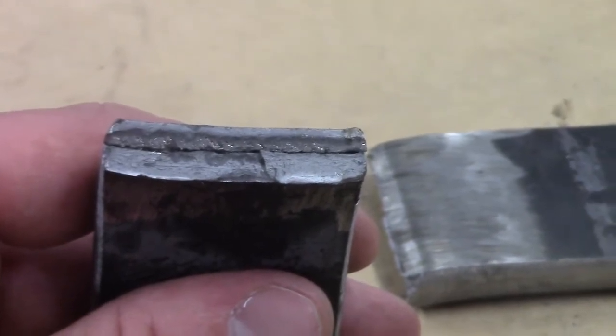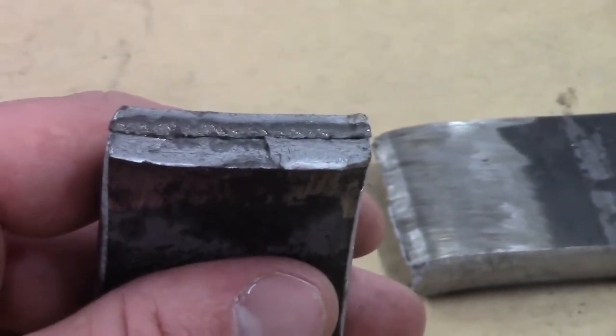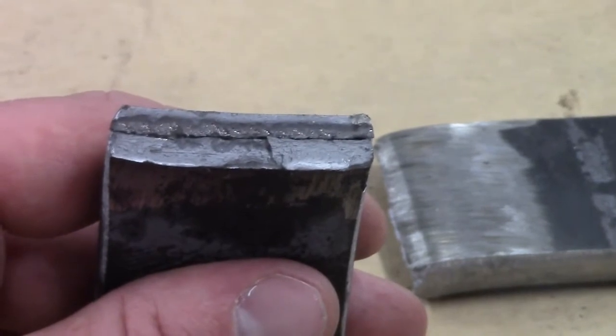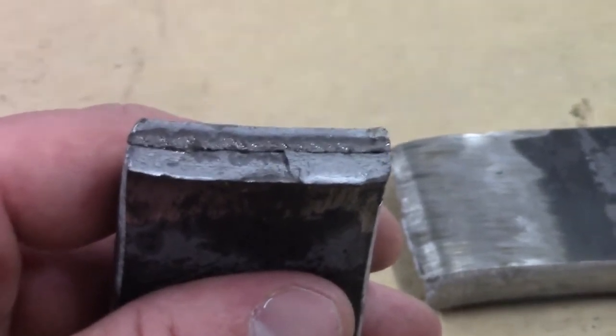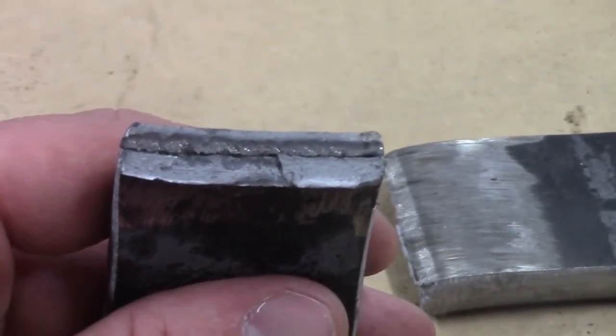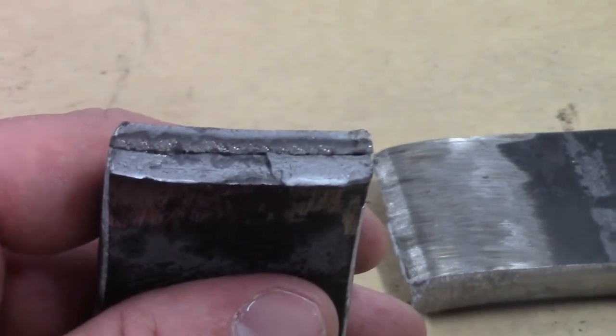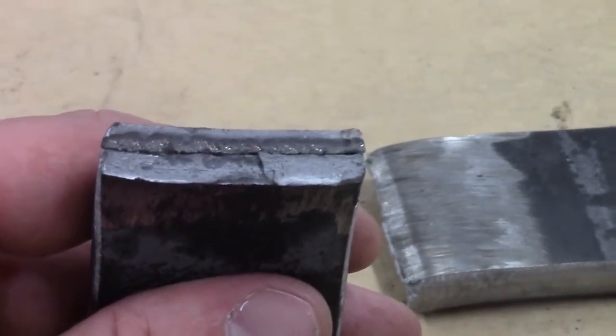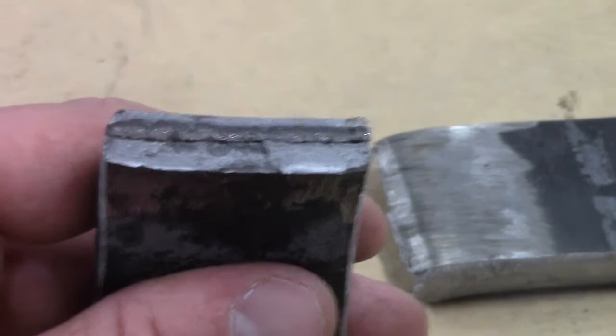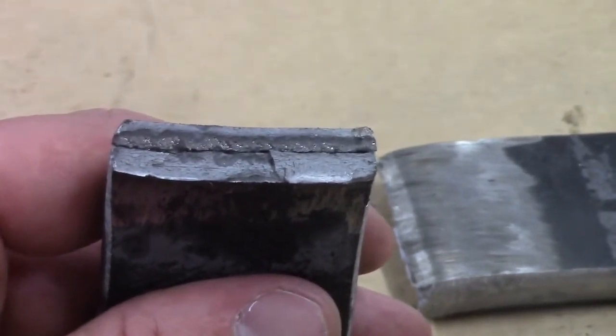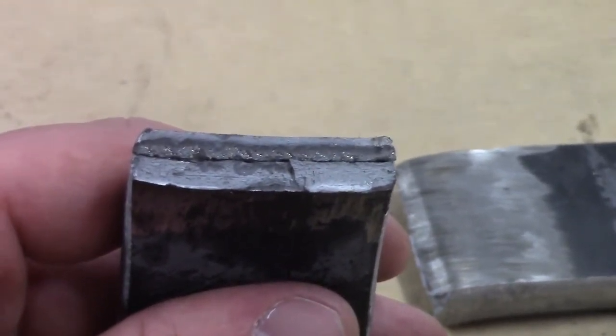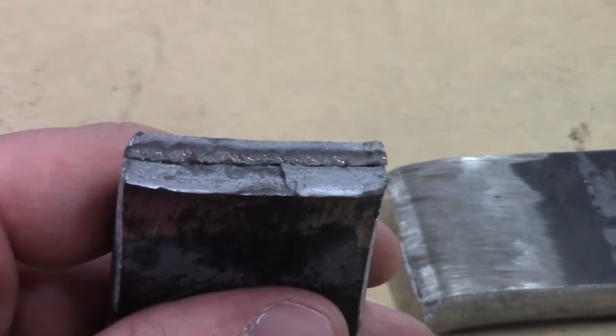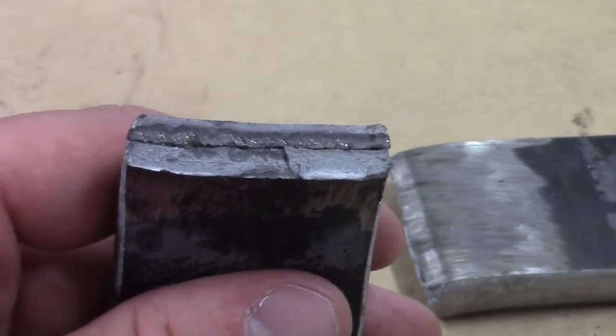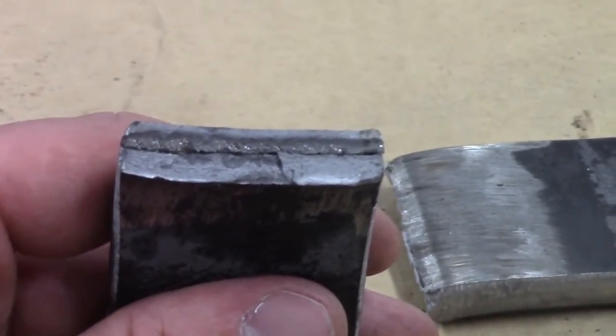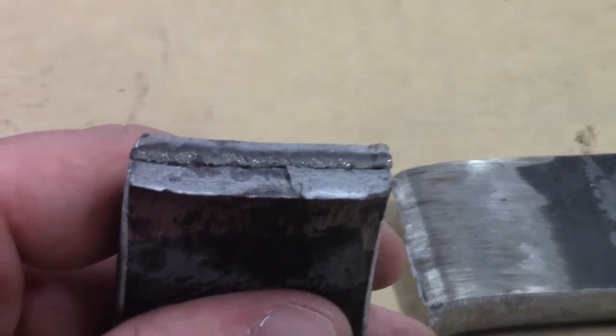This was probably the beginning of the weld where you didn't have the preheat of the weld as it went down the plate, because the last one we bent actually bent and was successful, so it probably preheated it in the beginning to where you got at the end and it was acceptable. But let's take a look at the last bend that actually is going to pass, and we'll take a look at the cracks and determine why it passes.